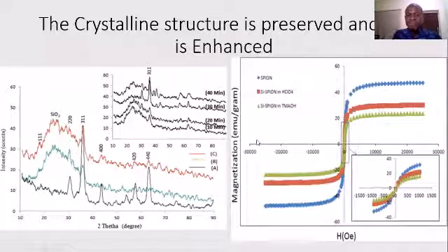And how about the saturation magnetization of the iron oxide? We find that despite the iron oxide being incorporated into silica, the magnetic property of the iron oxide nanoparticle is enhanced and is intact. Here, in this work, from the lab of Prof. Afzal Abdulaziz in Universiti Sains Malaysia, we are able to show that